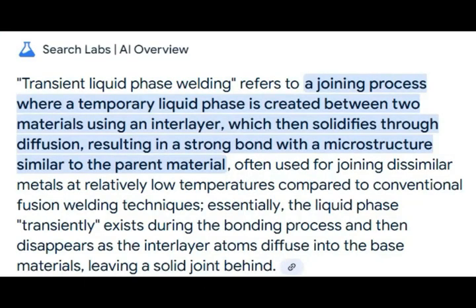join aluminum to steel. Transient liquid phase welding refers to a joining process where a temporary liquid phase is created between two materials using an interlayer, which then solidifies through diffusion, resulting in a strong bond with a microstructure similar to the parent material, often used for joining dissimilar metals at relatively low temperatures compared to conventional fusion welding techniques. Essentially, the liquid phase transiently exists during the bonding process and then disappears as the interlayer atoms diffuse into the base materials, leaving a solid joint behind.